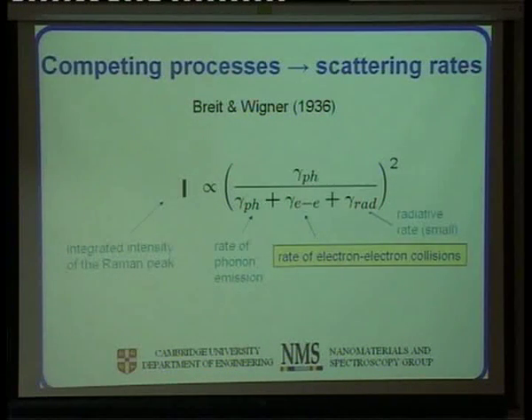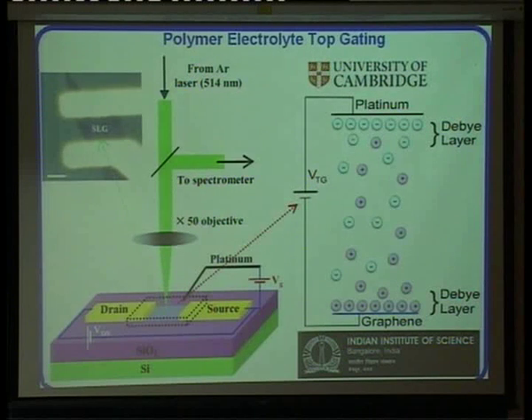So the intensity of the Raman spectrum depends on the electron-phonon coupling, but also the electron-electron interaction and the radiative rate, which is quite small. And so we could modulate the intensity, as I mentioned before, if we can change, for example, the electron-electron interaction. And this was a very important work that was done here at the Indian Institute of Science in collaboration with us, where Ajay first, and we sort of got the idea from them.